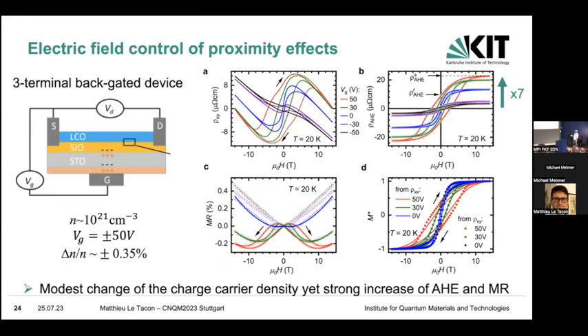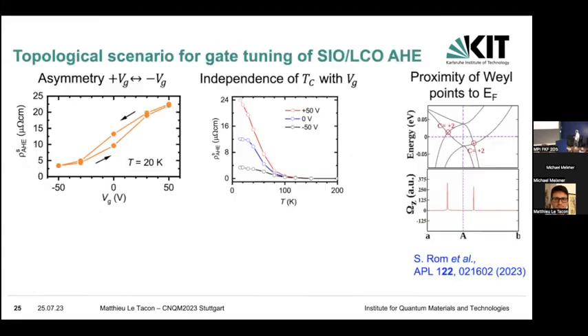Yet when we look at the anomalous Hall effect here, you see this nice hysteresis curve, and you see that this strongly depends on the applied electric field. Actually, from -50 to 50 volts, we have an increase of almost an order of magnitude of the amplitude of the anomalous Hall effect, both of the saturation value here at high field and of the coercive field. And the same thing goes with the magnetoresistance. So this very modest change of the charge carrier density gives a very strong increase of the anomalous Hall effect.